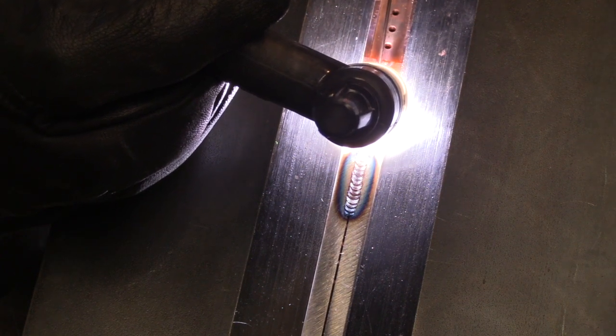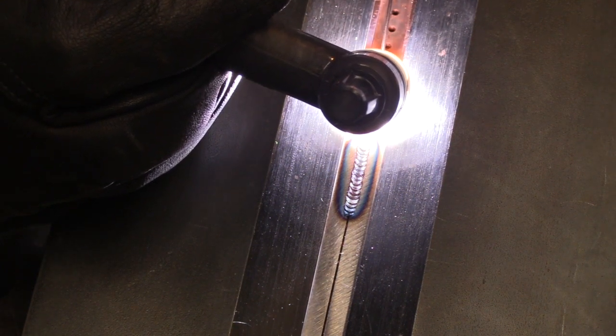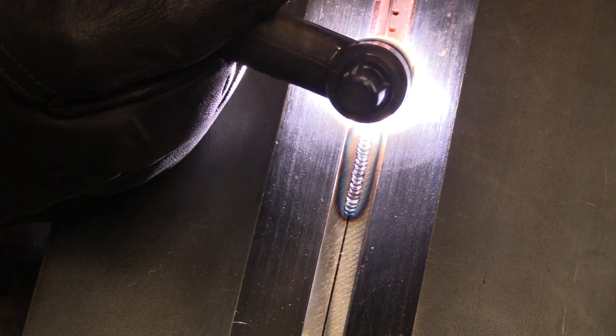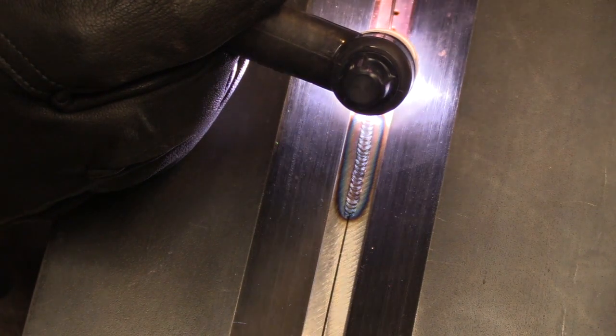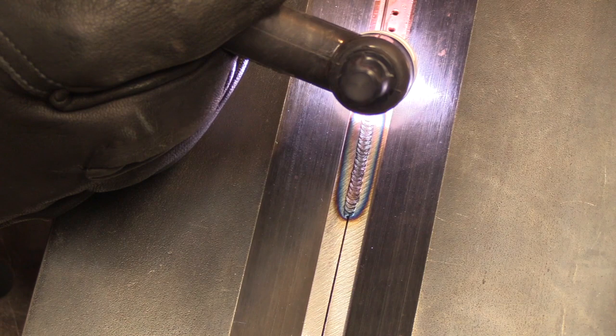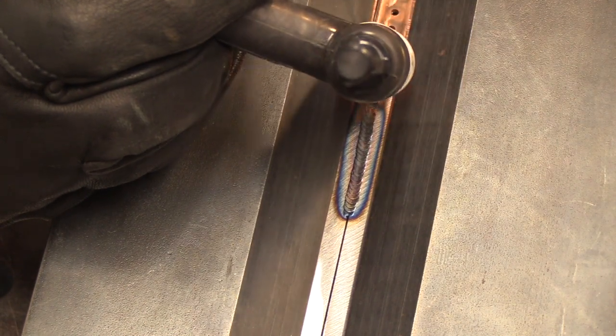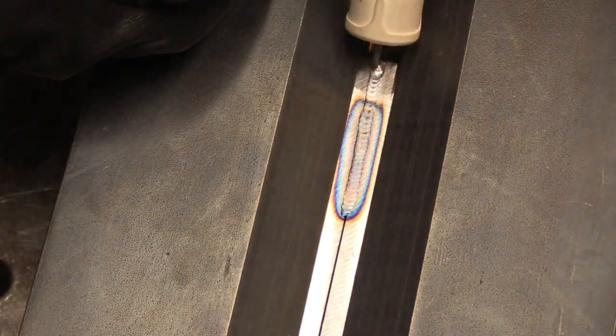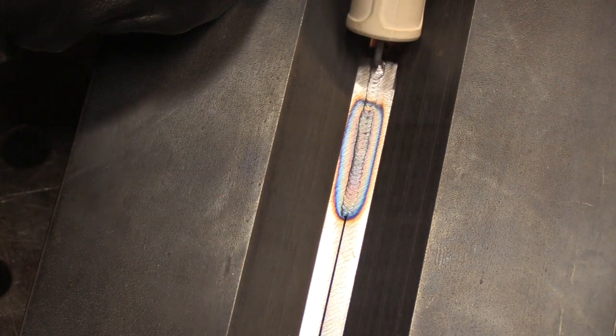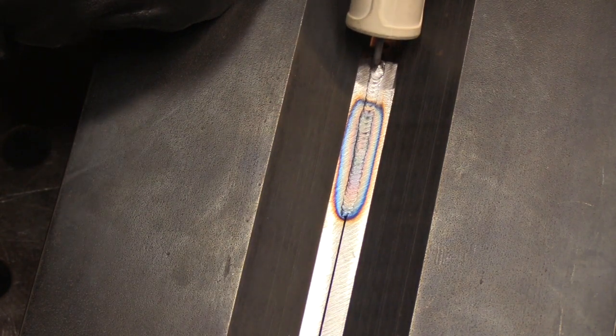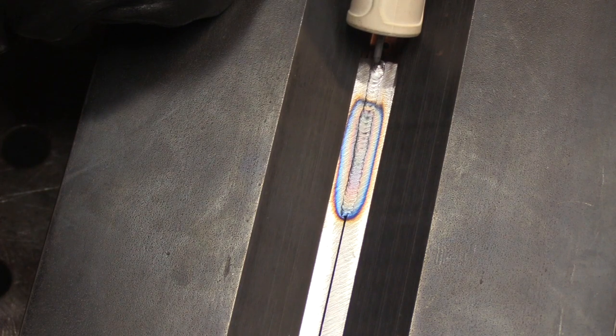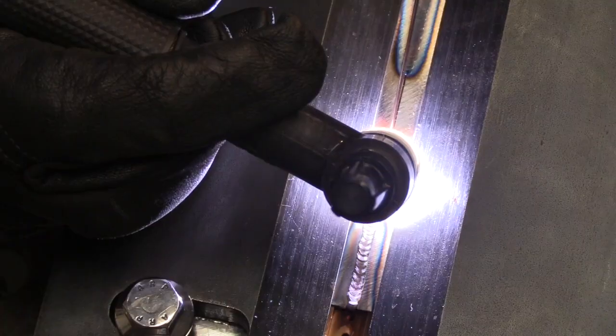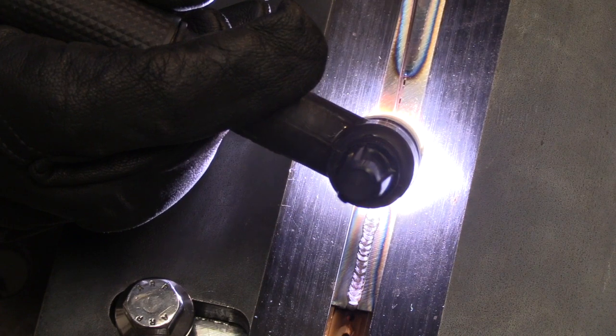There's slight differences. 200 pulses a second is a lot. And what it does, it stiffens the arc up, but it's almost like welding without pulse. There's some really subtle differences. In a lot of cases, I would prefer to do this type joint with no pulse at all, but you know, the machine's got it, and so I like to experiment. That's how we learn.